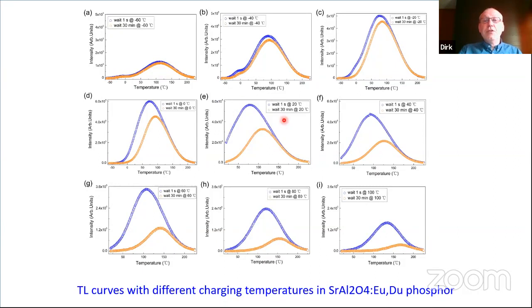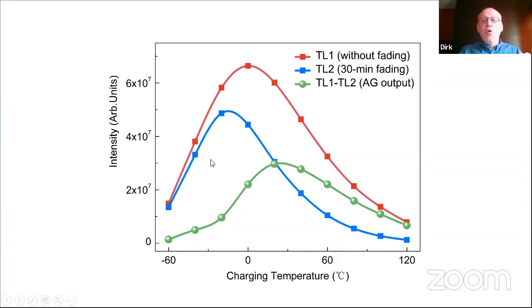For example, here, for us, it's room temperature, 20 degrees centigrade. There's a big difference between the thermoluminescence measurements without waiting and with 30 minutes waiting. And so the difference between these two curves gives an idea about how much light is emitted during half an hour at 20 degrees centigrade. So we can make a graph of the difference between these two curves as a function of temperature. And this then gives us an idea of how well the persistent phosphor performs at a certain temperature. And this graph shows this.